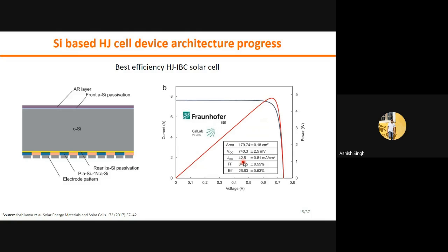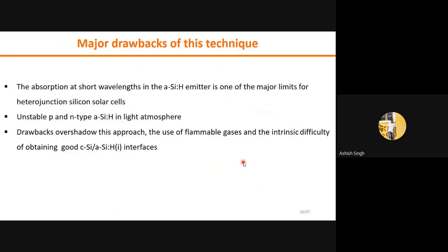But this technique is not free from disadvantages. The major disadvantage in this technique is the light absorption in amorphous silicon. That limits the current density of the heterojunction solar cell. Even this amorphous silicon is unstable in light atmosphere, so due to this the cell reliability will decrease with time. So that is the major problem in this technique.